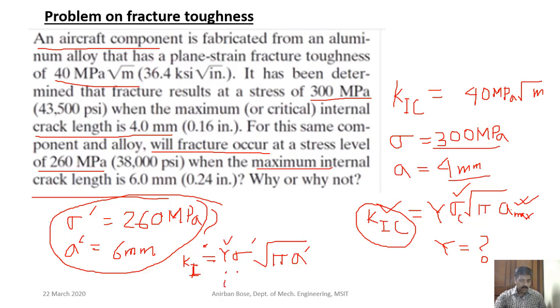Now if this K1 is more than or equal to K1C, then fracture occurs. If not, then fracture will not occur. Okay, so this is how we can solve the problem.